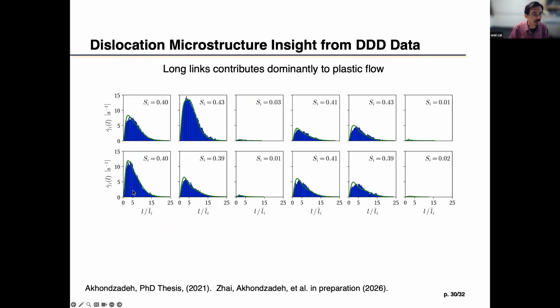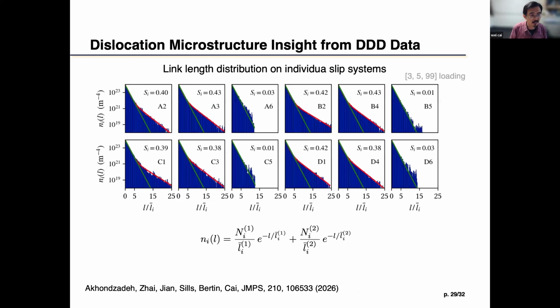And you see it's very interesting that its peak comes from links of length that are 5 times the average link length. But for the integral value, there's actually a lot of contribution from very, very long links. These are very rare links, but very, very long. So basically, even though these have very low statistics in terms of number of links, in some sense they are the dominant contribution to plastic flow.